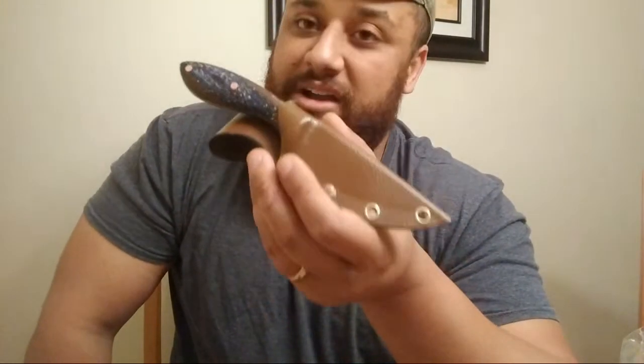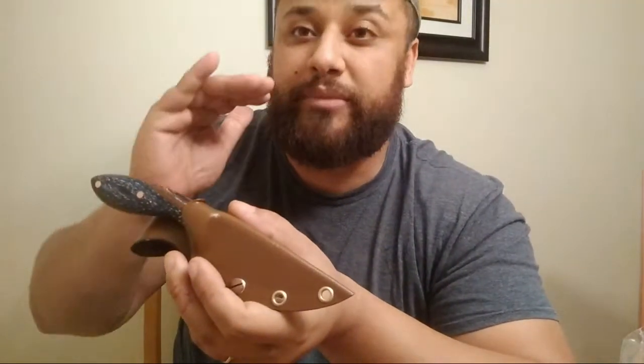the better it is to shape the apex to 1 micron and submicron, basically in the nanometer length, because after you have a micron length, you have nanometers, okay? Because you have 1,000 nanometers for 1 micron. Just to give you a scale of how small that is, red blood cell coursing through your veins is about 8 microns. You can't see a red blood cell with your naked eyes, right? That's pretty fucking small. And so for something to be about 1 micron and under a micron in the nanometer scale, then you have a really, really fucking fine edge.